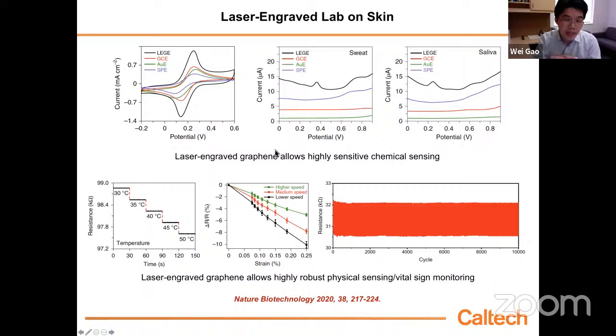We can use this to monitor temperature. In this case, when the temperature increases, the mobility of this graphene increases, resulting in a decrease in resistance. Basically, a graphene-based temperature sensor has a negative temperature coefficient.